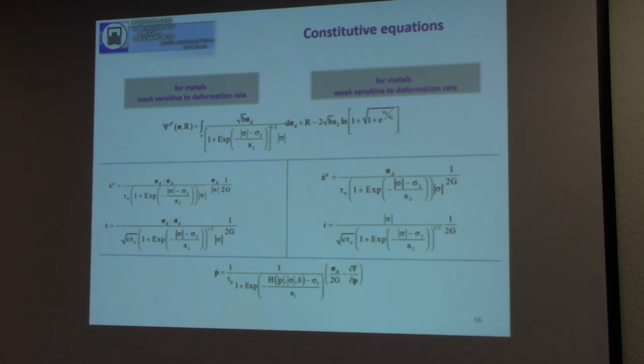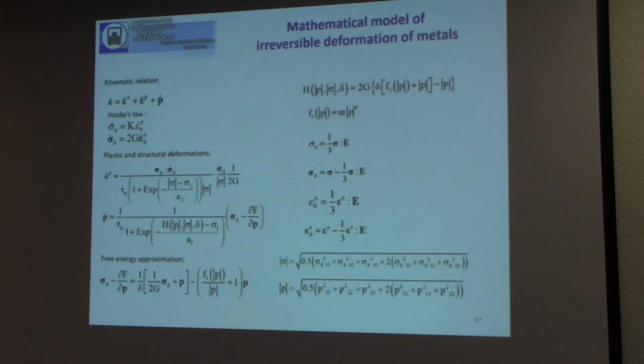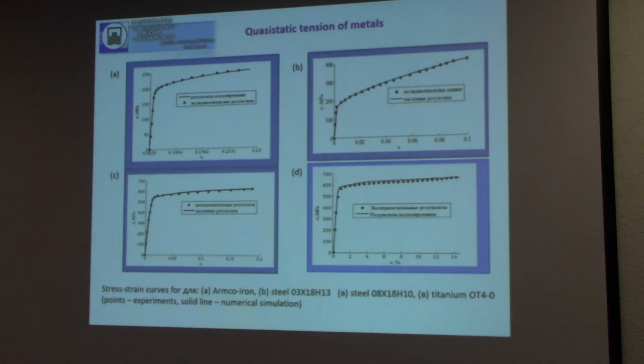Finally, we used two different versions of our model: weakly sensitive to deformation rate and sensitive to deformation rate. In this model, we have two parts. The dissipative part, which is practically classical plasticity, and an additional part which describes the energy stored in our ensemble. We can forget about the Kachanov ensemble. It's just a phenomenological parameter which can be used for simulation. And here you can see a set of equations which can be used for simulation, and some examples of our